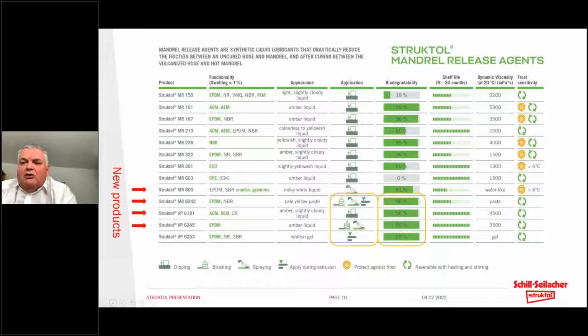More recently, there are much more efficient automated application techniques that involve spraying a measured amount of the lubricant into the core of the hose directly on extrusion. And for that reason, you need some kind of paste or gel product, which either undergoes thermal softening or shear thinning and can be dotted down the surface of the hose to provide the release built into the hose prior to fitting on the mandrel.